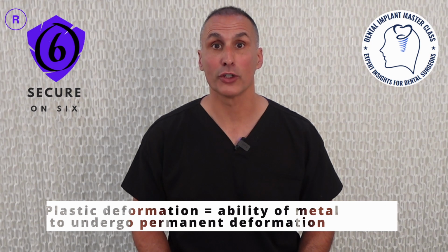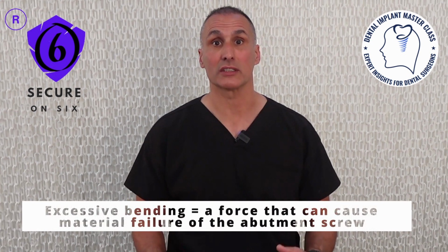Plastic deformation refers to the metal's ability to undergo permanent changes in shape. Excessive bending therefore reduces the contact forces between the abutment and the implant, making the screw joint more susceptible to loosening. Another mechanism that contributes to screw loosening is the fact that no surface is perfectly smooth. Even meticulously machined implant components exhibit microscopic roughness, causing the surfaces not to make full contact. Consequently, when external loads are applied to the screw interface, micro movements occur between these surfaces.